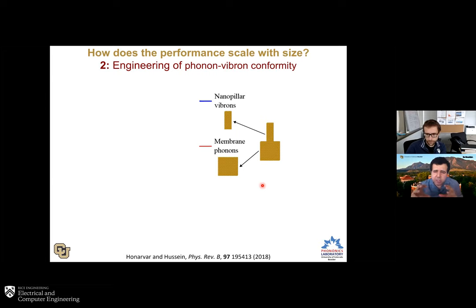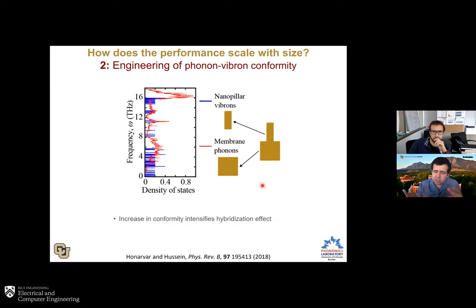So if we take our unit cell, which is a membrane with a pillar attached on the top, and dissect it, so we turn it into a membrane portion and a pillar portion, all right? And then if we were to calculate the density of states for each of those components, this is what we get here. So in red, we have the phonon density of states. It's a familiar distribution if you're familiar with bulk silicon, because it looks quite similar to that of bulk silicon, even though it's a membrane. And then we have in blue the density of states for the vibrons, the phonons in the pillar, the standing phonons. Immediately, you'll see that they're not conforming.